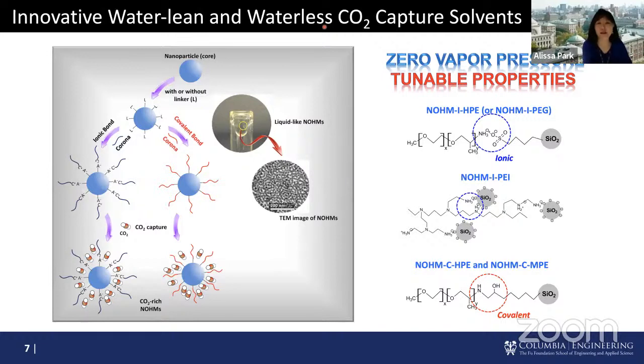And Lynden called me one day and said, Alissa, we made these really interesting materials by tethering polymers with the right size, right grafting density onto nanoparticles. The final product, as shown here, is a liquid-like material. And what he said was, this is really interesting because there's so much chemical and physical tunability. At the same time, it has almost zero vapor pressure and is very thermally stable. So I thought it was a really fascinating material because we have to do a lot of temperature swing and thousands of cycles for CO2 capture, so if I can decorate all these NOHMs with a lot of amine functional groups, perhaps we can make a waterless material that still behaves like a liquid for CO2 capture.